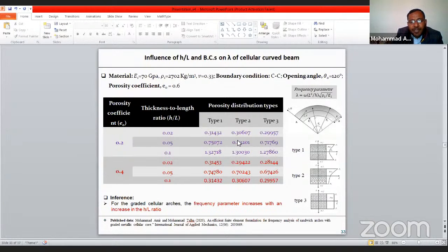We observed that on increasing the h by l ratio from 0.02 to 0.1, the frequency parameter also increases. Of course, with increasing porosity coefficient, the frequency parameter depends upon the type of porosity distribution used. I will explain it later.